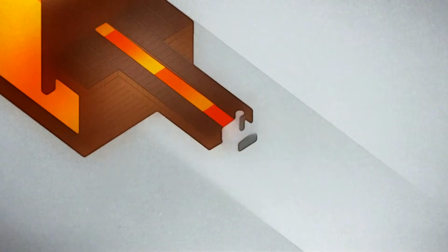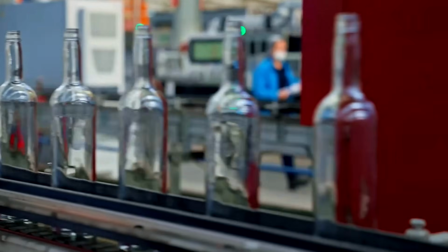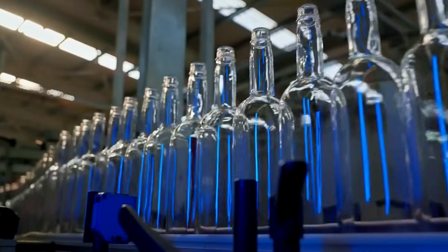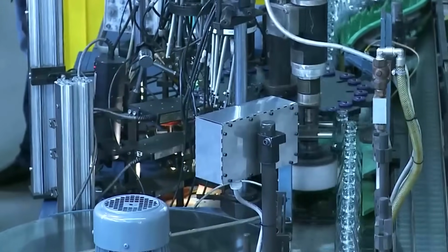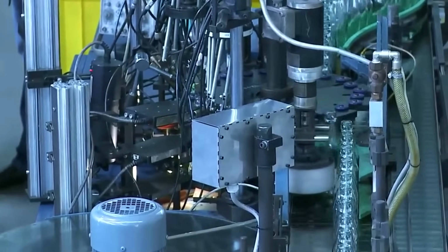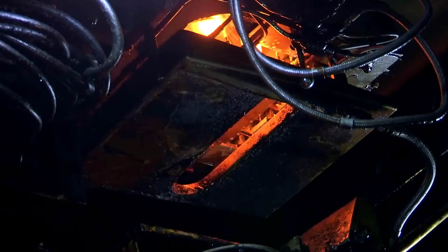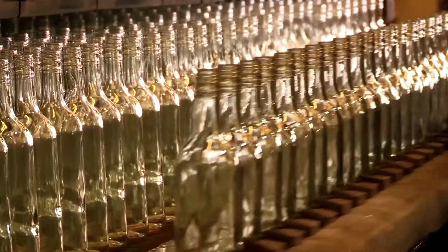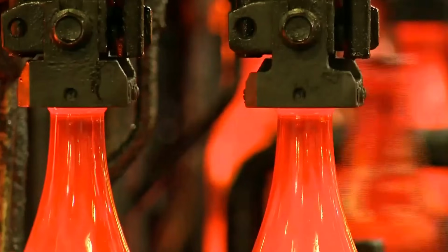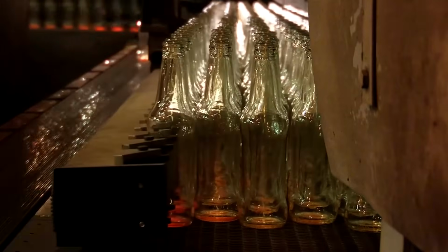Why is the addition of recycled cullet strictly calculated before the melt? The mix undergoes precise blending to guarantee uniformity before reaching the furnace. Adding just 10% more cullet reduces overall energy consumption by about 3%, significantly lowering carbon dioxide emissions.